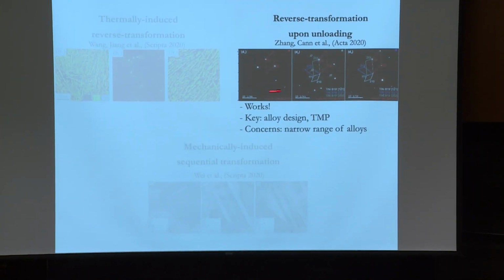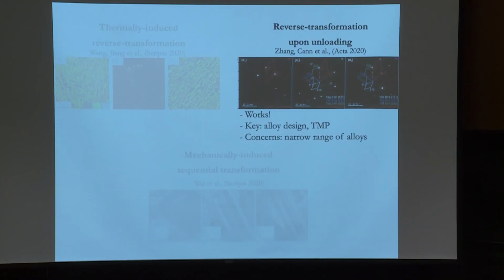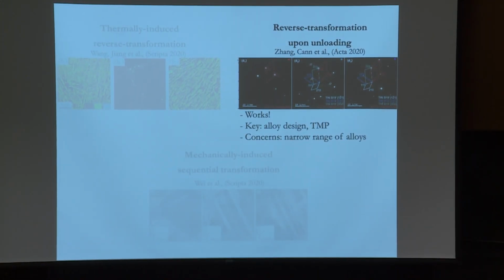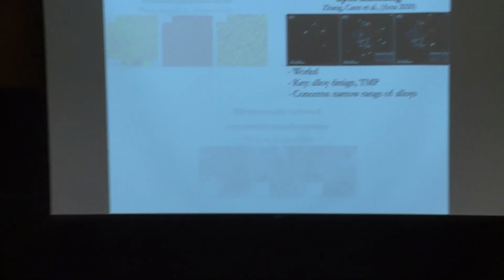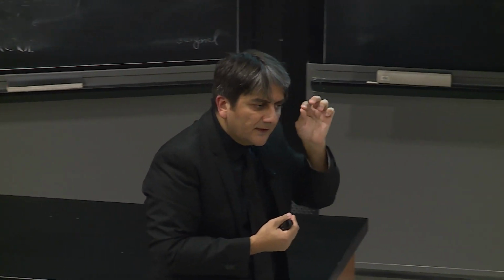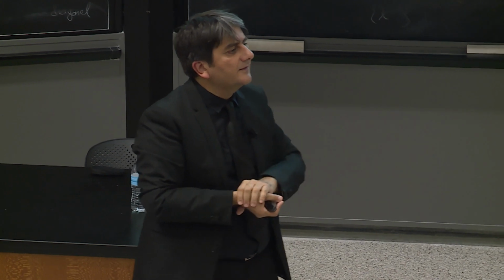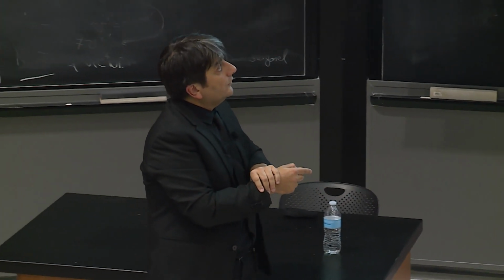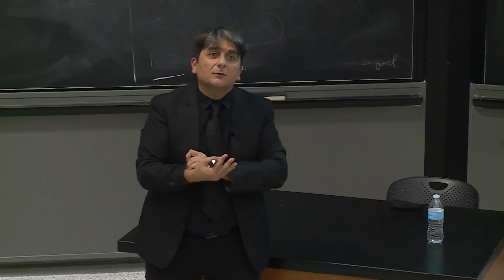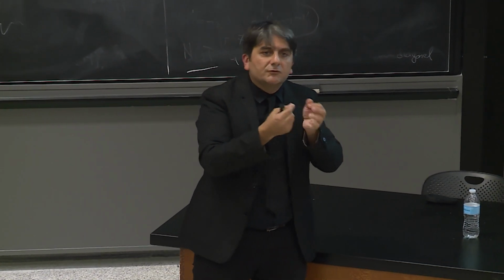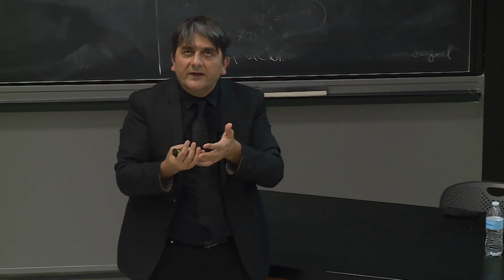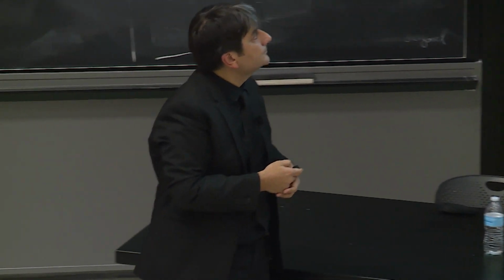Right, so the second solution to our problem is having the reverse transformation when you unload. And this seems to work, but again, the key idea here is alloy design, so that you can have this phase that exhibits this behavior. The concern, of course, is that you can create this kind of behavior only in a narrow range of alloys. You need to be able to introduce a superelastic second phase in the right dimensions, in the right phase, to be able to have benefits of this. So maybe not too good of a solution.